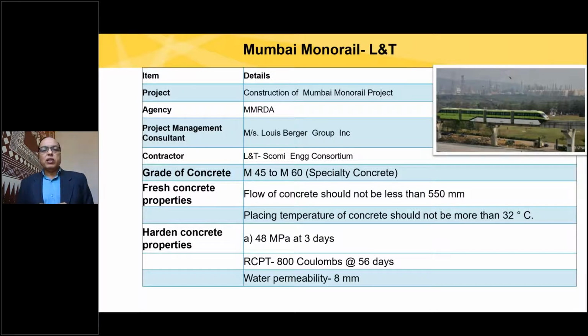Their requirement was two varieties of concrete. One was M45, another M60. And again, look at the flow of concrete. The flow of the concrete in this project should not be less than 550 millimeters. So much flow it should have. And then the placing temperature should not be greater than 32 degrees. Now, look at the concrete properties.